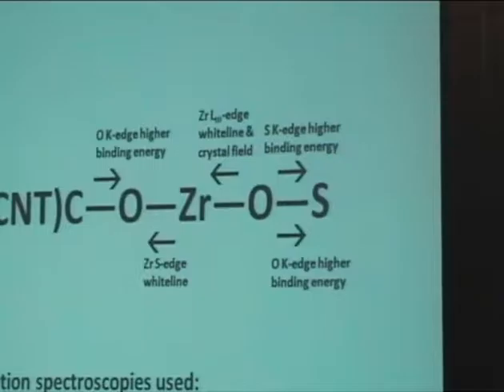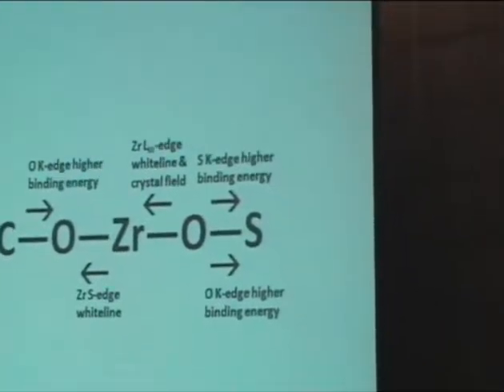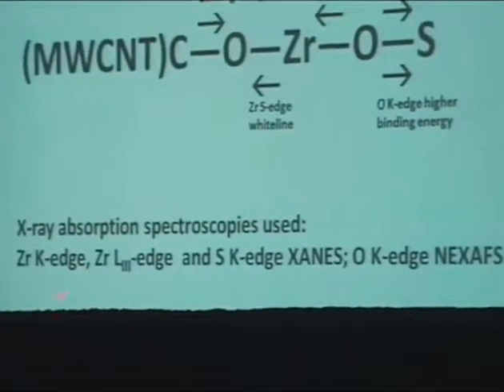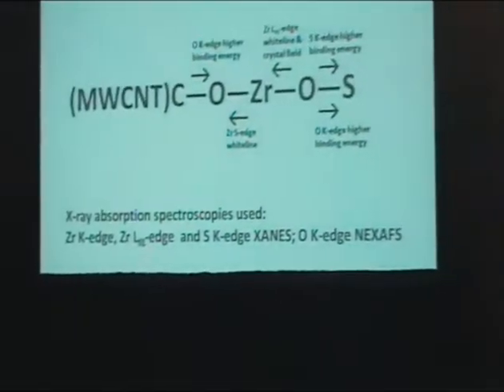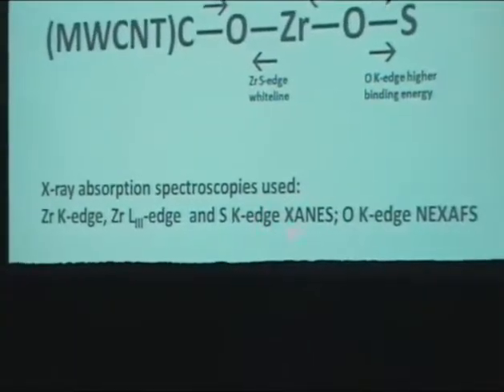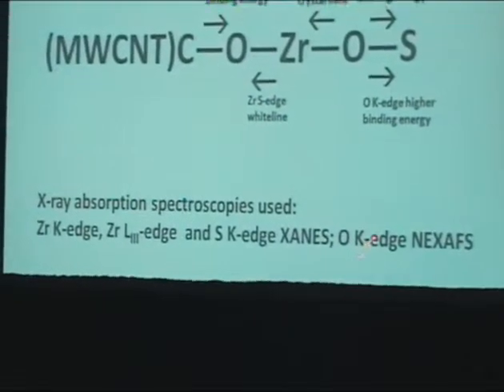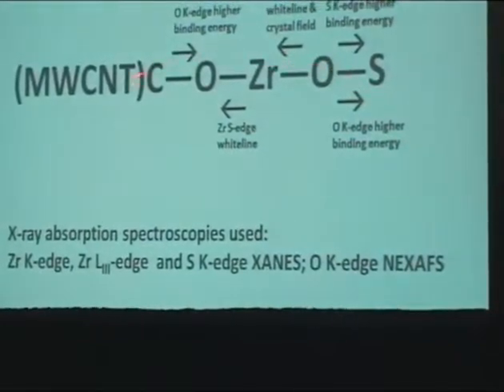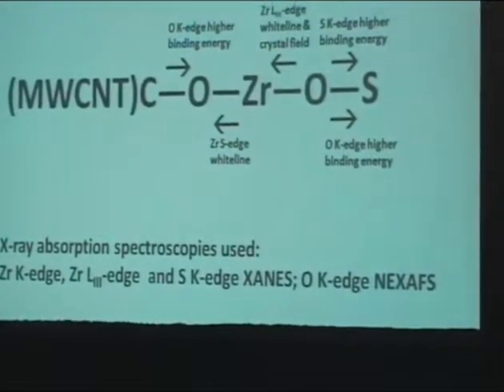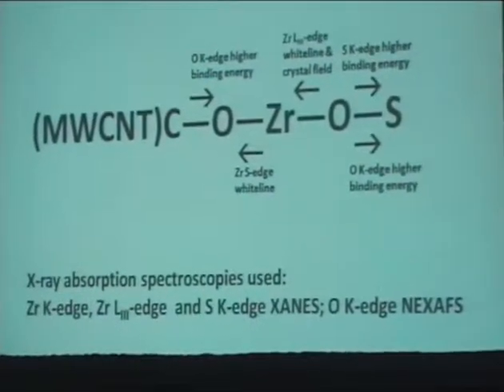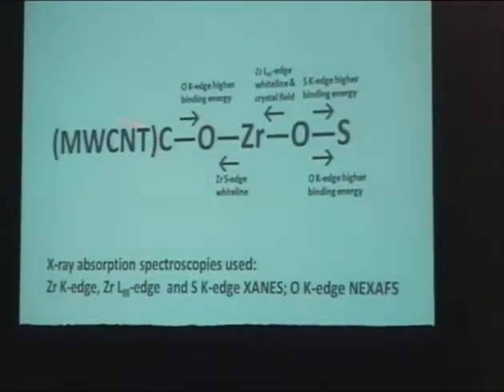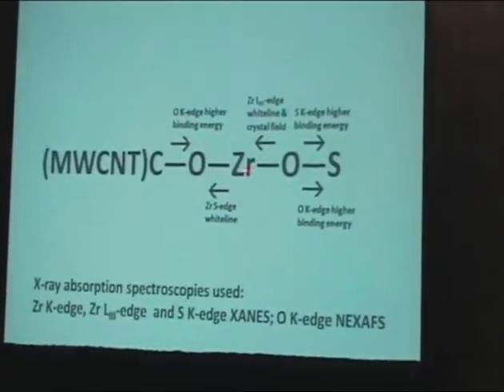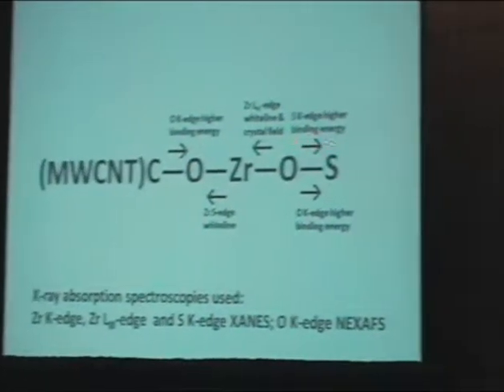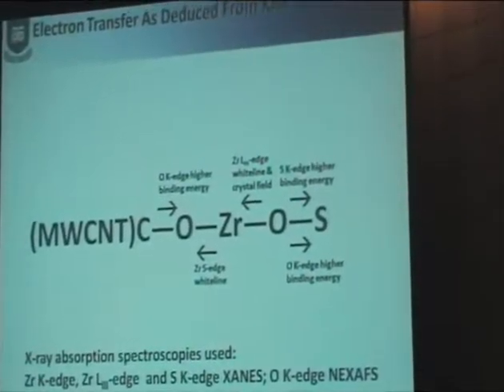So here is a whole bunch of electron transfer, which has been studied using X-ray absorption spectroscopy. I'm not going to go through this at the moment, that's kind of a summary, but we're going to tune to the X-ray K edge of zirconium, the L3 edge of zirconium, the K edge of sulfur, in all cases XANES, no EXAFS, and also we're going to do NEXAFS on the K edge of oxygen, to try to deduce this flow of electrons from the different atoms in the structure, where I'm representing it simplistically as carbon bonded to zirconium through oxygen, and then sulfur also being bonded to oxygen to zirconium.